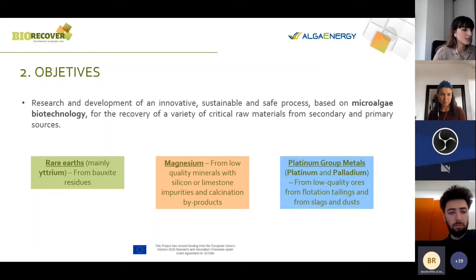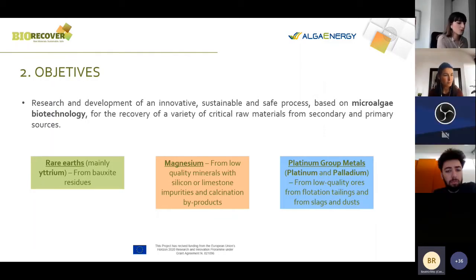The following critical raw materials are intended to be recovered with high recovery capacity, selectivity, and purity, using microalgae as a biosorbent. Rare earths, mainly yttrium from bauxite residues, magnesium from low-quality minerals with silicon or limestone impurities, and calcination byproducts, and platinum group metals, platinum and palladium, from low-quality ores, from flotation tailings, and from slag and dust.